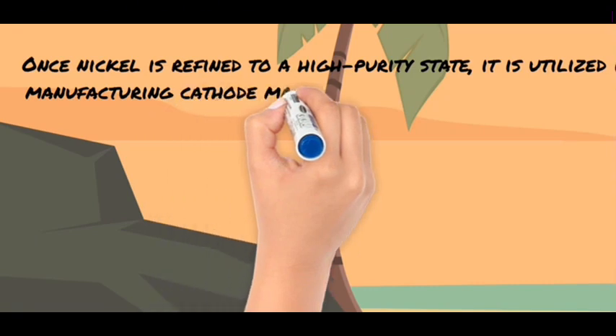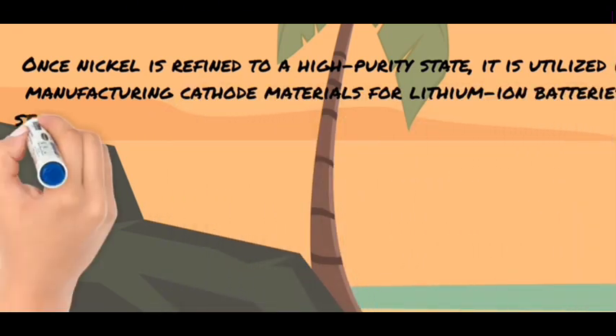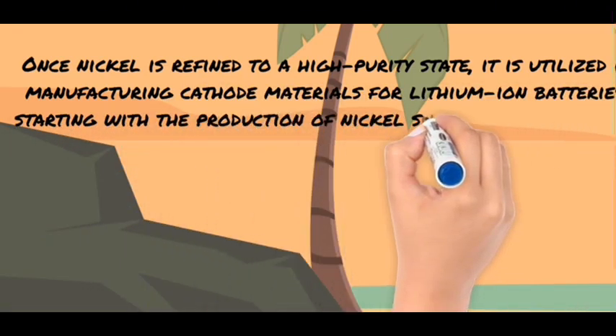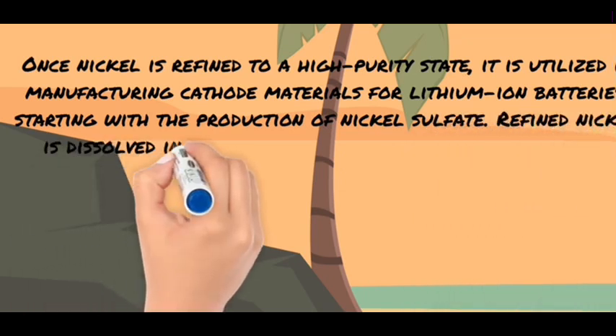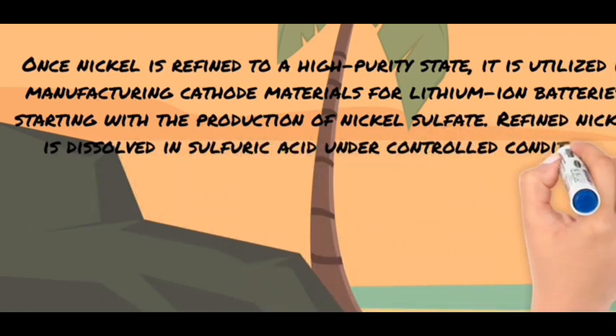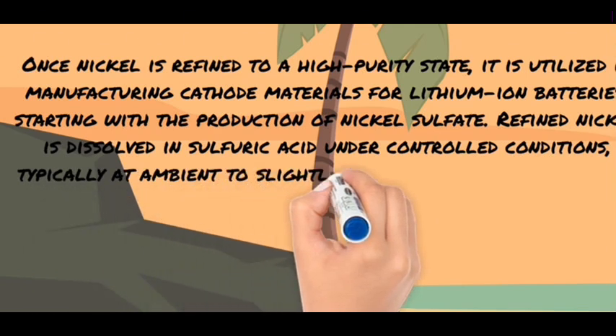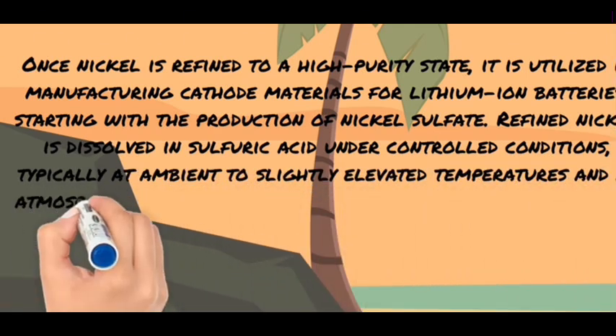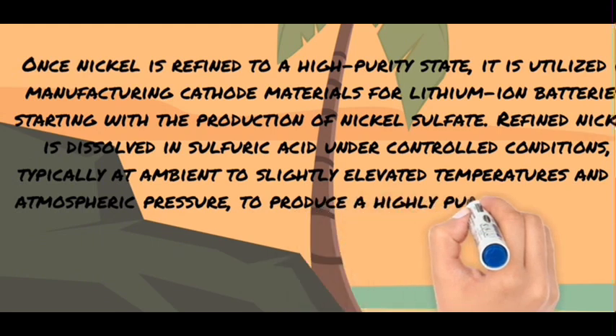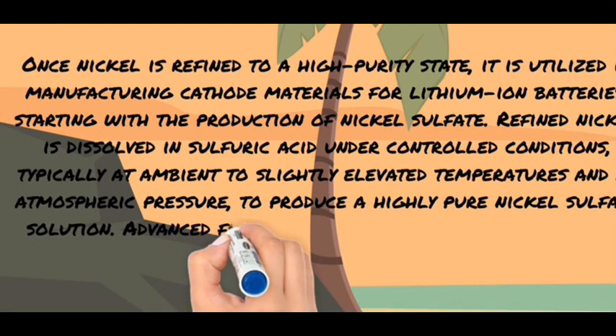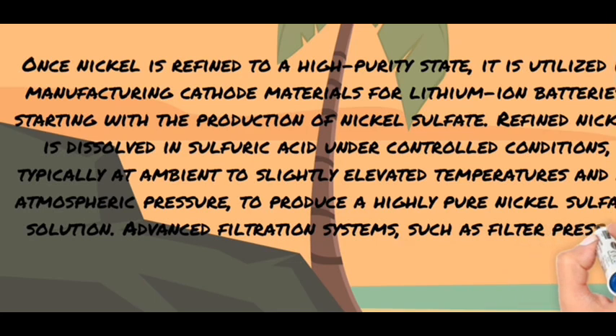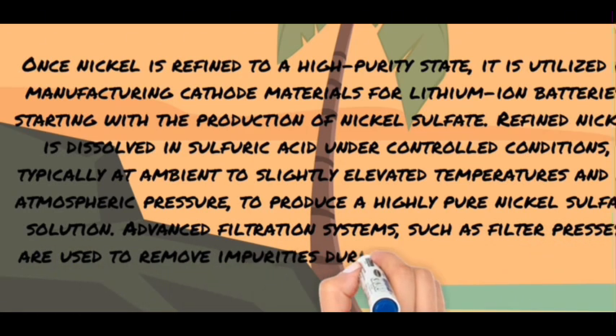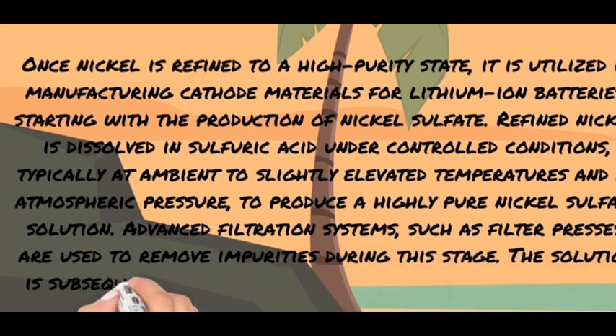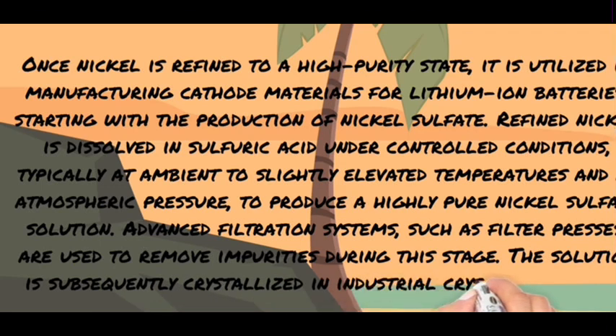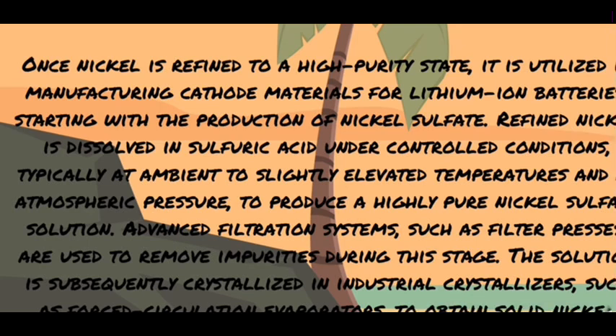Once refined, it is utilized in manufacturing cathode materials for lithium-ion batteries, starting with the production of nickel sulfate. Refined nickel is dissolved in sulfuric acid under controlled conditions, typically at ambient to slightly elevated temperatures and at atmospheric pressure, to produce a highly pure nickel sulfate solution. Advanced filtration systems, such as filter presses, are used to remove impurities during this stage. The solution is subsequently crystallized in industrial crystallizers such as forced circulation evaporators to obtain solid nickel sulfate crystals.